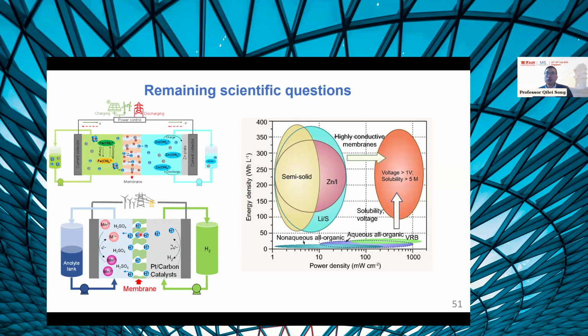And also, if we want to use this membrane in the acidic flow battery, for example, this hydrogen manganese flow battery, we have also developed membranes that can facilitate the transport of protons and also with higher stability against the degradation by the metal ions. And there are many other flow battery chemistries. So generally, we need to develop highly conductive membranes to enable the operation of the battery device.